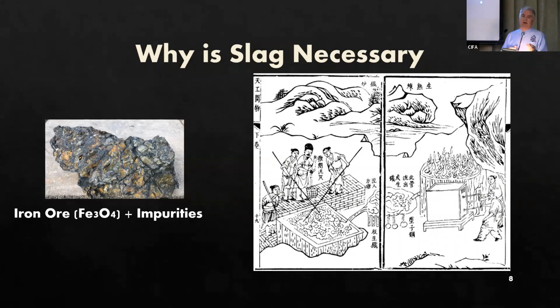In addition, sometimes other impurities come along with the slag. For example, coal, like anthracite or bituminous coal, or coke, or charcoal might come out with the slag. You might have solid pieces of iron ore and limestone that don't quite melt in the furnace. They'll come out with the slag. Sometimes ash residue from the combustion of the fuel will come out in the slag. And then sometimes even the lining of the furnace comes out along with the slag. It's not desirable, but nevertheless it happens.